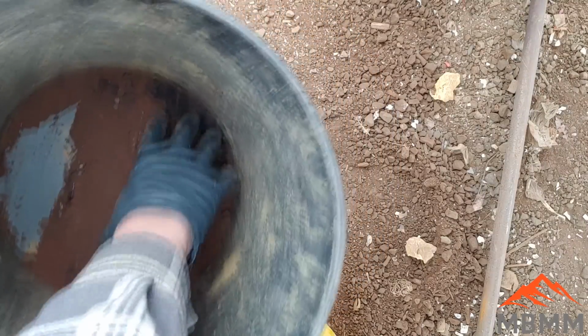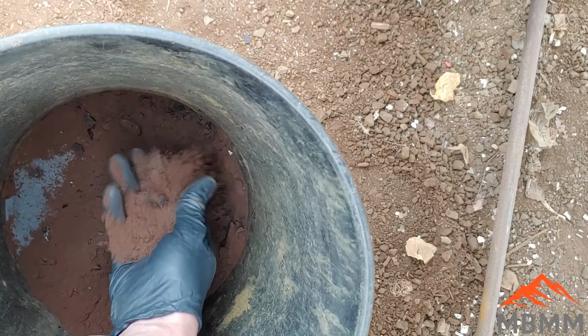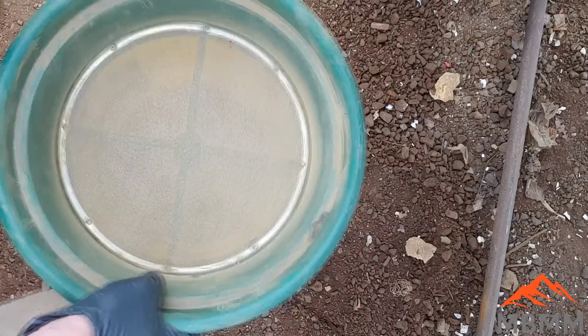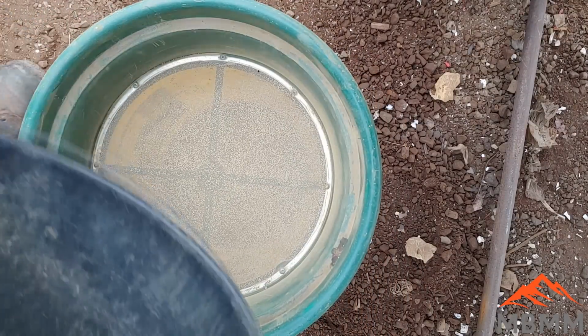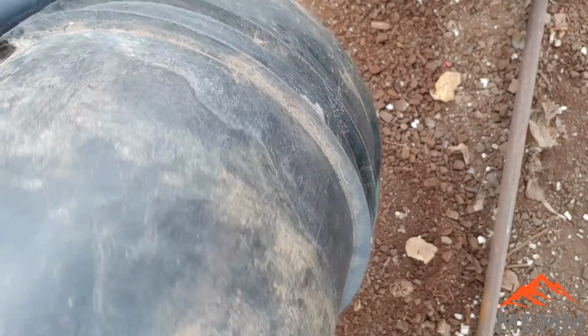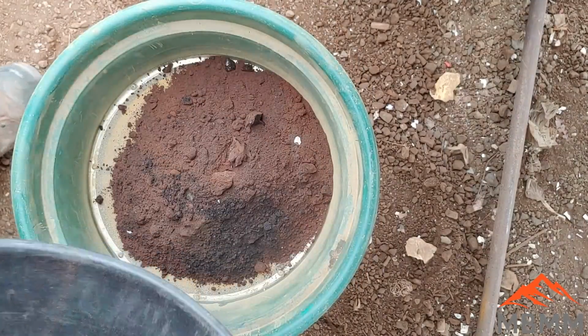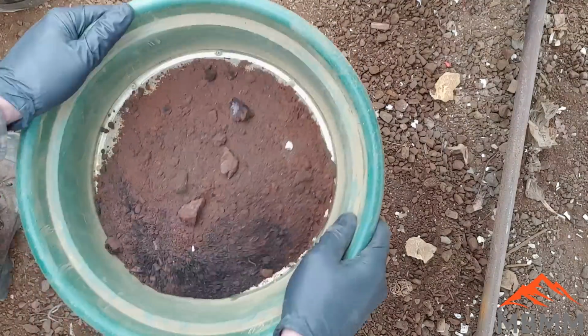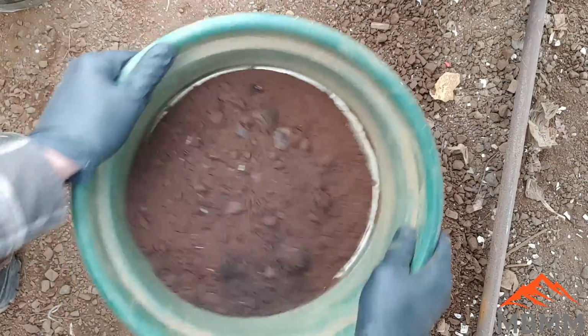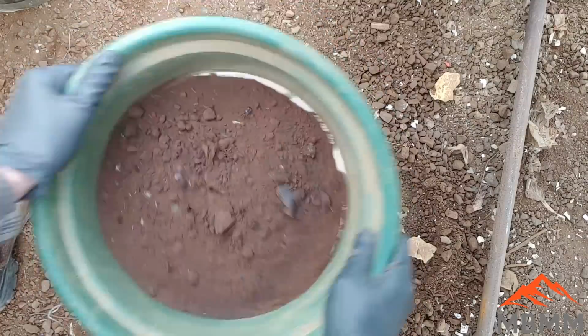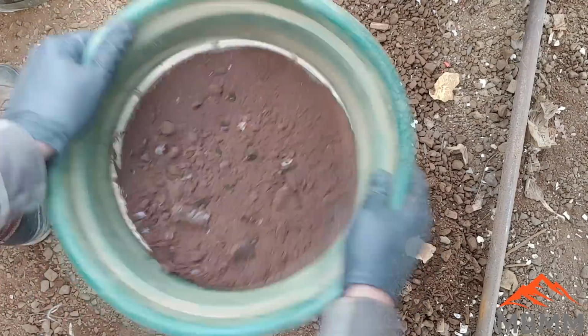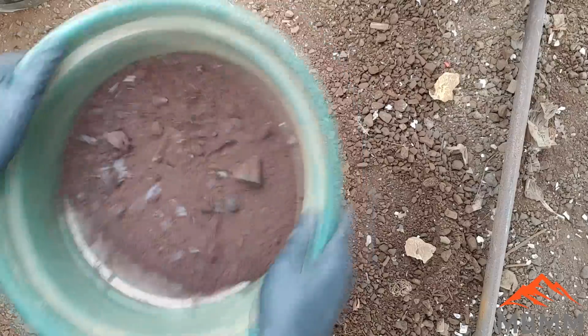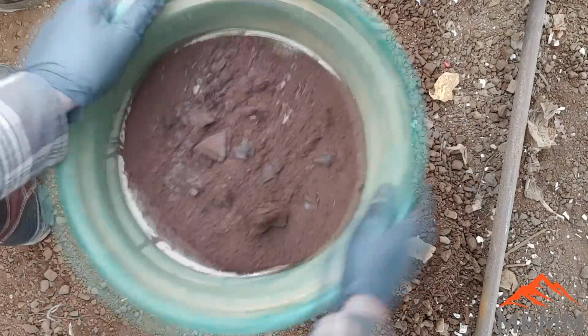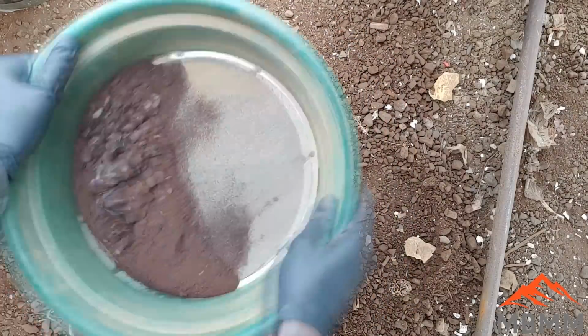Our first job here is we're going to take our kind of powdered matte. We're going to screen it through a 50 mesh screen here and get the big chunks out. And then I'm going to try to just direct smelt this powder down and see if it's still sulfides or if they've been converted to oxides by the water in the air or the oxygen in the air when they sit out in the environment.